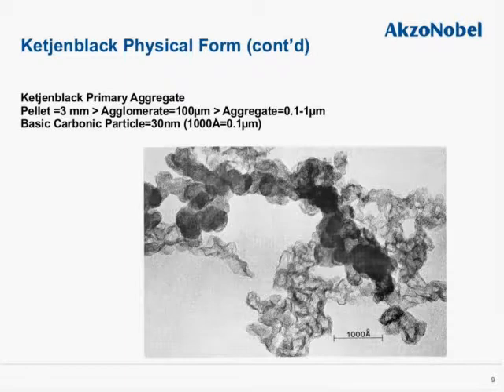Continuing with the physical form of Ketjenblack products, this is a picture taken under scanning electron microscopy. It shows the type of agglomerates that are formed, starting with the primary aggregate, which is the pellet, about 2 to 3 millimeters in size, and then broken down into various agglomerates and aggregates, down to a basic carbon particle, which is about 30 nanometers in diameter. So it's a very, very fine particle. And I'm going to go into details later on why this very fine particle has unique properties.